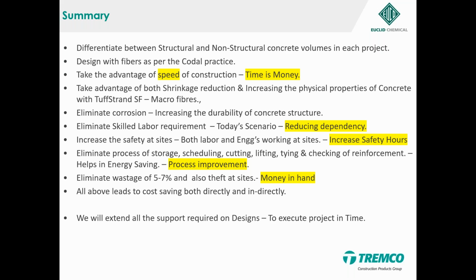So all these things lead to direct and indirect savings to the project, other than improving the durability and integrity of concrete. I was just telling the Doctor earlier, before starting the program, that when slag and fly ash have started replacing cement and making it more durable, I think we should look at whether we can replace steel in the non-structural part of the structure with fibers, and add value to the project, make it durable, and also reduce the dependency on manufacturing steel, which is a very big process by itself, in cost and in energy.